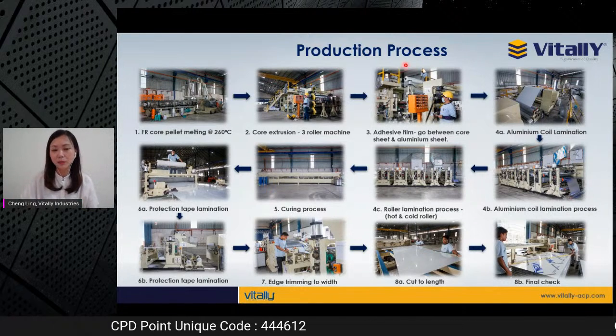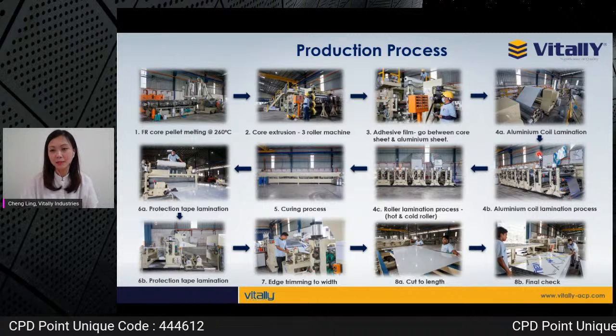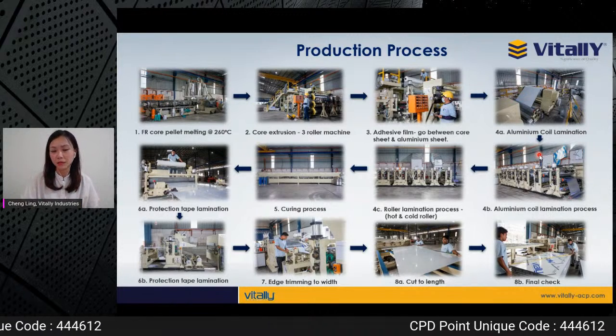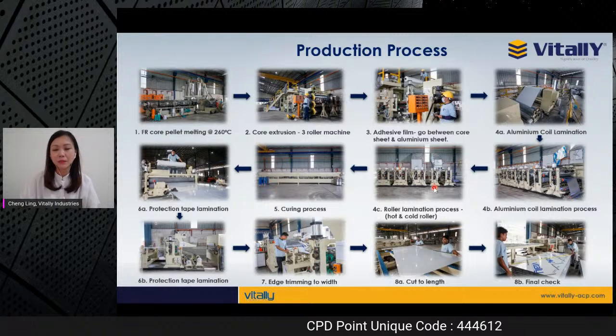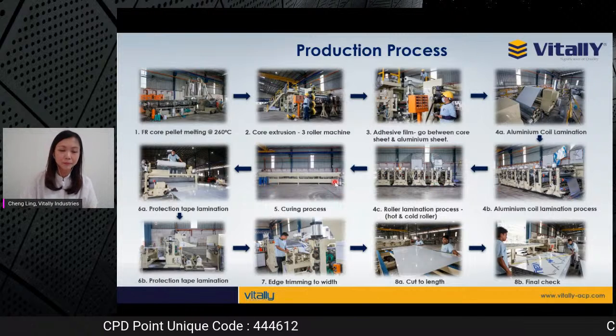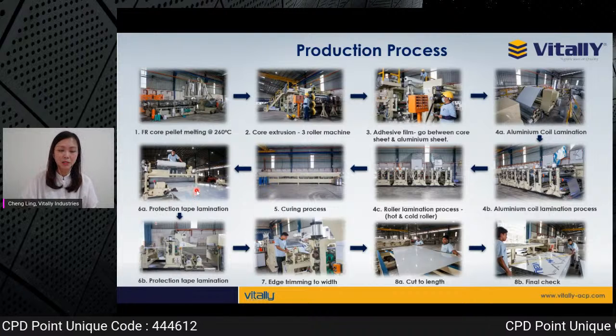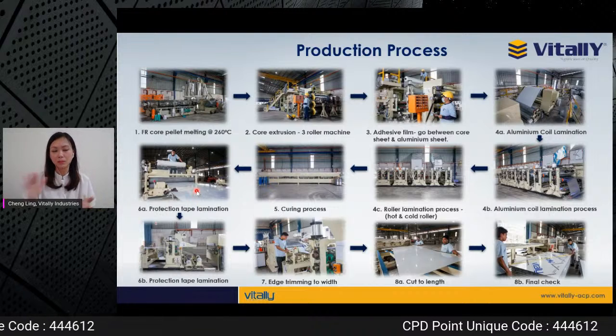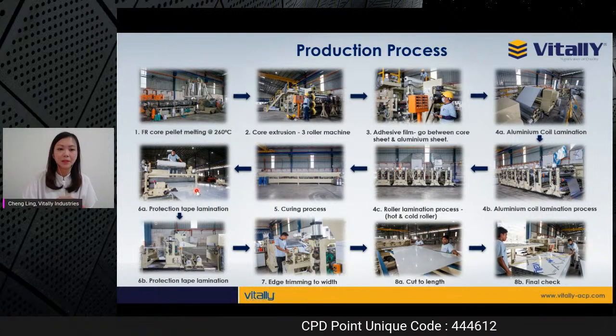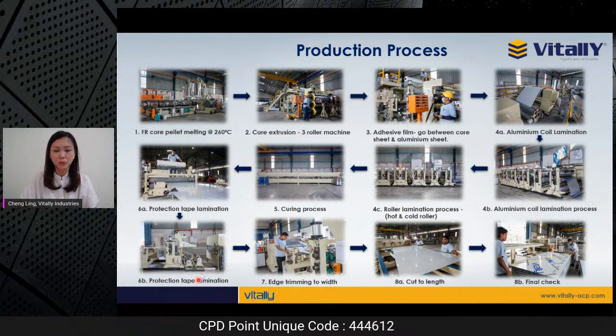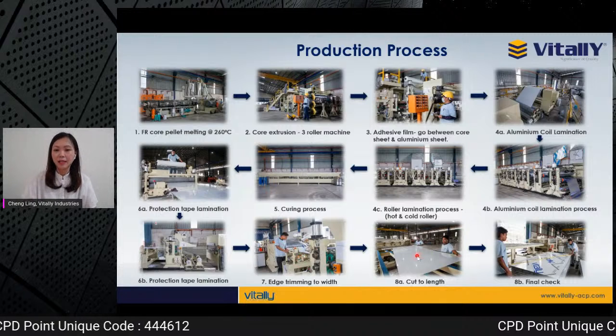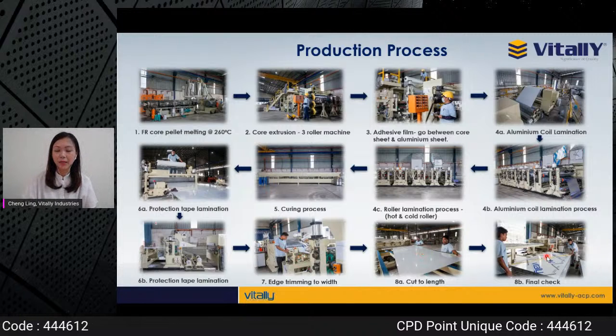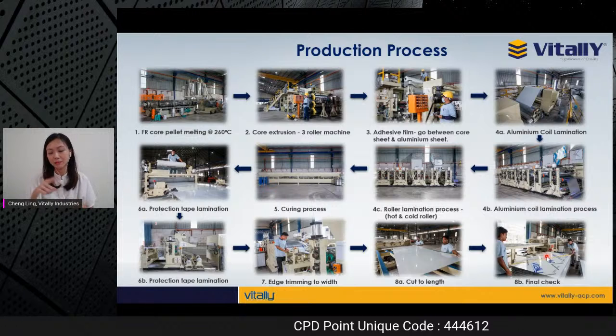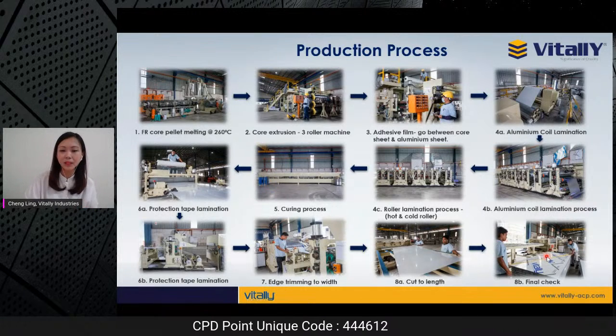And then that's where we start the lamination of the aluminum skin, with 2 layers of aluminum skin on top and at the bottom, right? After that, it goes through a cooling chamber and the curing process, followed by the lamination of the protection tape on top of the coating surface. After that, we do the trimming process and then cut to length. For the finished product, we do a final check of the panel dimension, right?